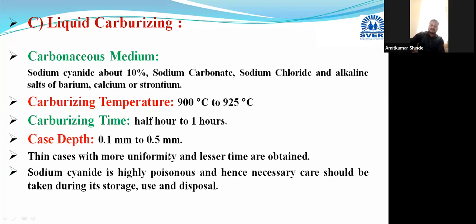If you compare gas and liquid, then with liquid we get thin case depths in lesser time. The disadvantage of liquid carburizing is the sodium cyanide which we are using here as a source; it is highly poisonous in nature. Hence, proper care should be taken during its handling, use, and disposal. It can be hazardous to your health.